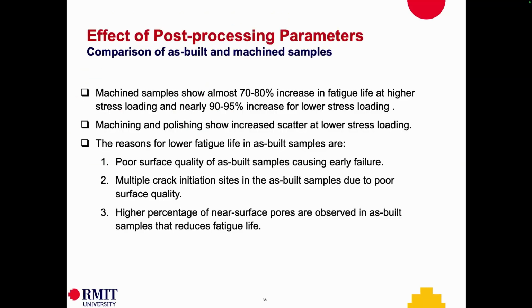So let's move on. So this is the summary, what we have learned from our experiment, and of course, analysis of data about how the post-processing parameters affect as-built and machine sample. Machine sample shows about 80% increase in fatigue life, and for the lower stress loading, it can be a double, 90% increase, but there is an increased scatter at the lower stress loading, which you have to take into account in your design. Finally, the surface quality is the key factor, which causes early failure. Multi-site crack initiation in as-built samples is a serious problem which we need to address. And the porosity, the large numbers and fraction of pores in the near surface also causes the failure. So this is a summary of what we found.